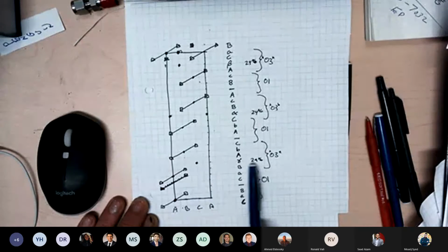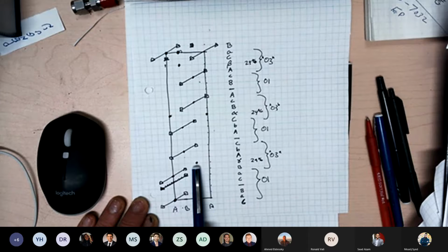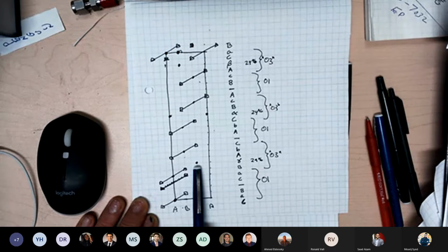That's what this 24% means: this lithium site has a probability of being occupied of 24%. It's probably actually 25%, which would make a lot more sense based on where the lithium atoms can go in between the layers. We'll talk about lithium ordering and these fractions like a third, a quarter, a seventh, and so on later on in the class.